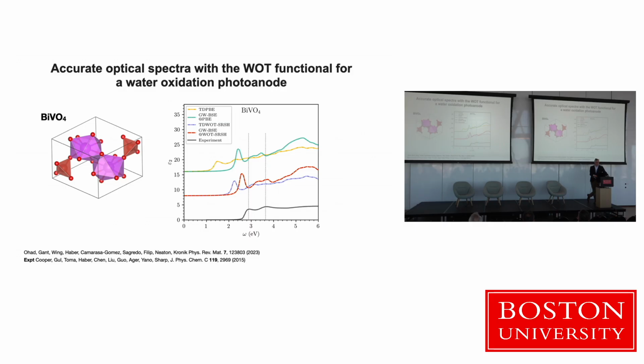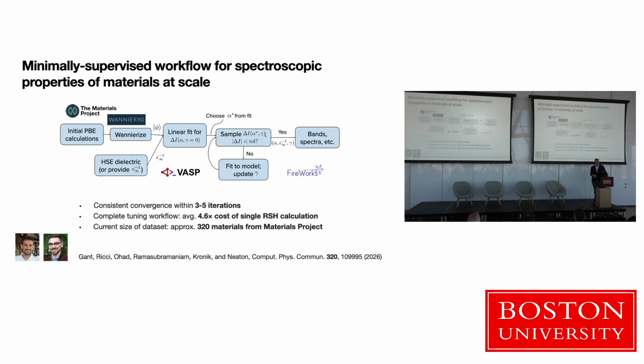It also works pretty well for bismuth vanadate without introducing phonons, of course, which is needed to capture more of this peak shape. But you can sort of see this is the state-of-the-art GW and BSE, and this is sort of the WOT value. So you're getting kind of spectroscopic information, but at less computational cost. It's still a hybrid calculation, but it's less computationally complex and costly than a GW calculation.